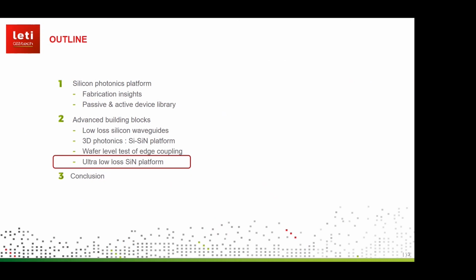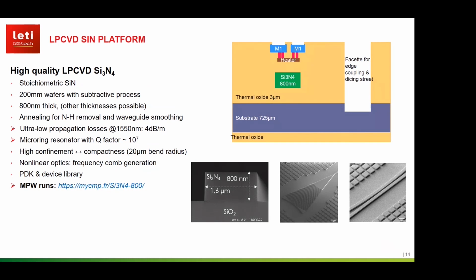So the last feature is a bit different from what I presented before. It's another platform, but I think it can be interesting for Datacom and for high data rate transceivers. It's silicon nitride only, based on LPCVD. So it means high quality silicon nitride with very low losses. Using this type of silicon nitride, we can have losses around a few dB per meter. So it's 1 or 2 orders of magnitude below what is done in PECVD, for example. And it means we can achieve ring resonators with quality factors of several millions with high confinement.